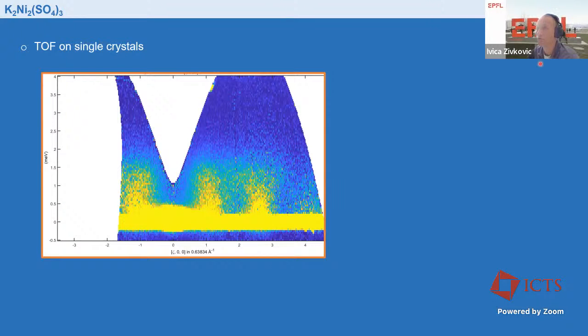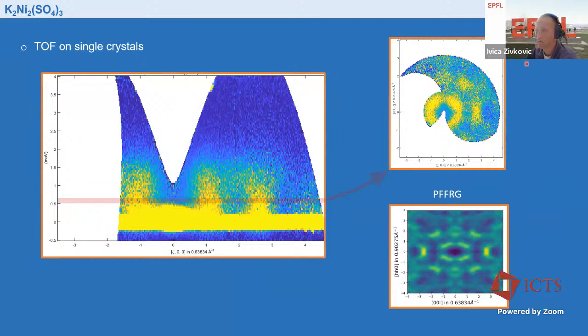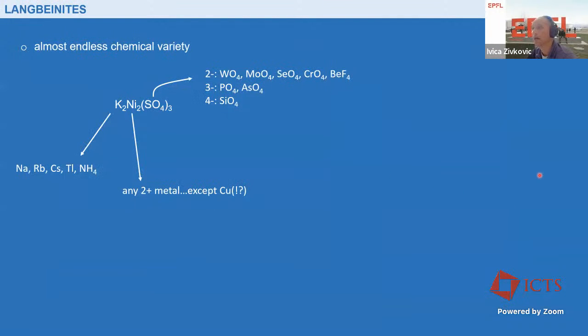Towards the end, we have also done time of flight experiments on single crystals. And if you look at those results, you can see that the features are completely non-dispersive. If you look at this cut, you can compare that to the quantum many-body calculations, and the agreement is actually quite good. We are still working on quantifying that agreement. And this is really coming towards the end, what can be done in the future.